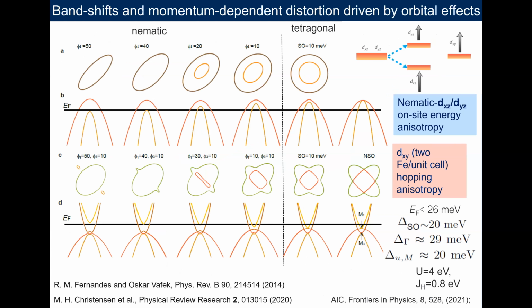And this is just some simulation of how the Fermi surface should evolve. When you turn on the nematic effects, obviously you will start to distort the Fermi surface and also shift the bands. So the hole bands, top band in relation to the bottom band, because this is where the nematic order parameter could be detected. And for the electron pockets, things will be much more complicated, but eventually we should expect to elongate these pockets. In reality, things are much more complex than this little cartoon.